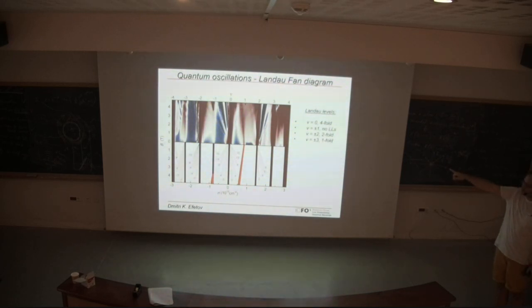So I think for a magic angle of 1.1 degrees, you would still want to go beyond 8 Tesla or so to really get into the Hofstadter regime. But for example, in the small twist angle devices, we get into the Hofstadter regime at like 2 or 4 Tesla.